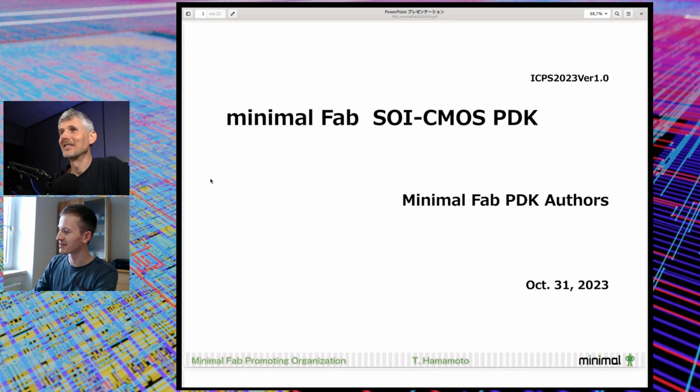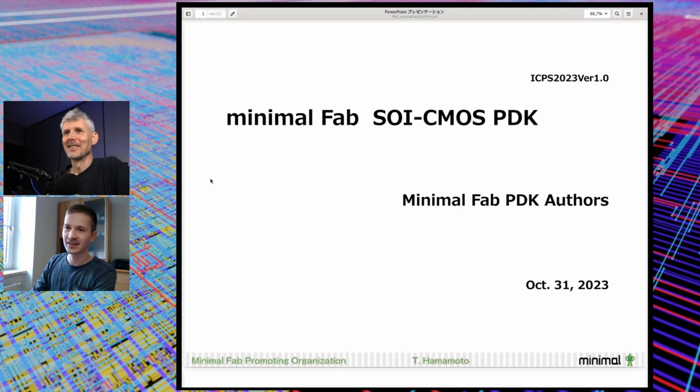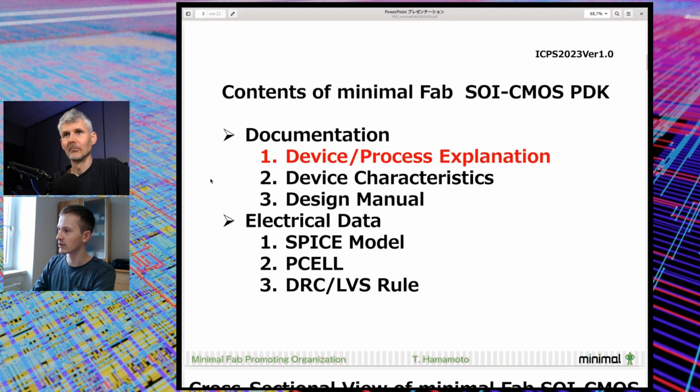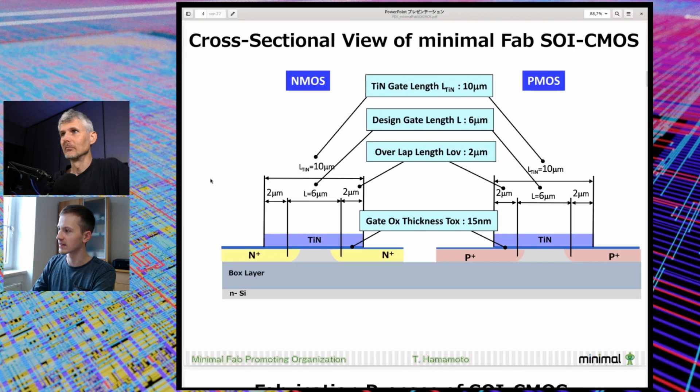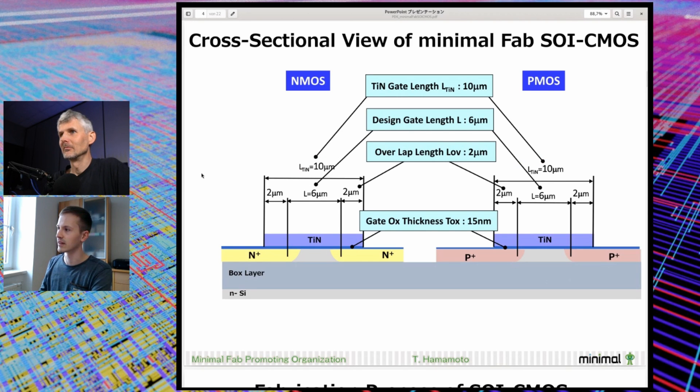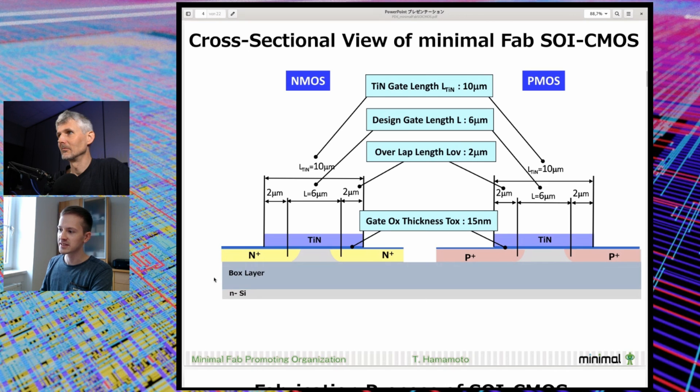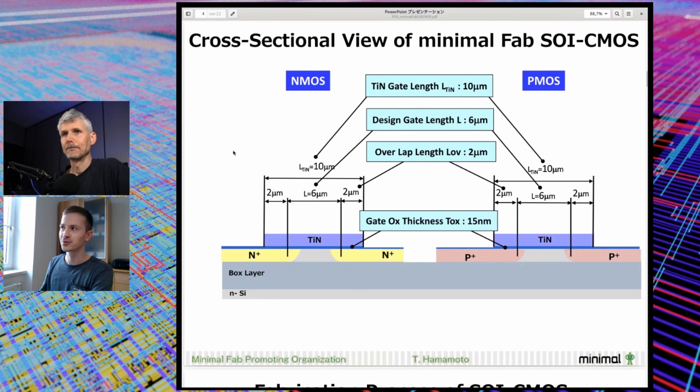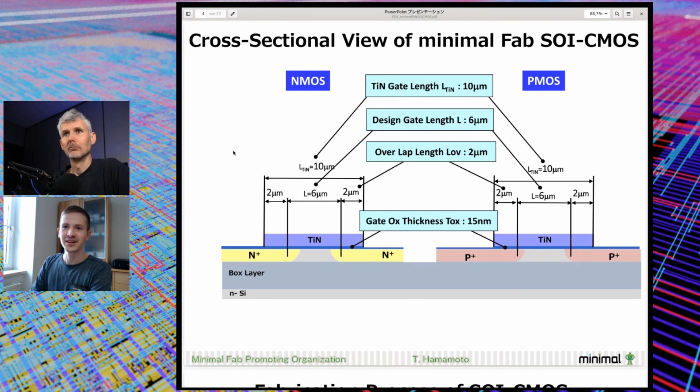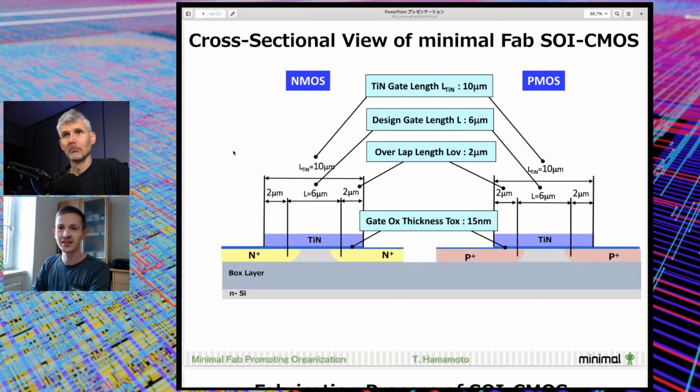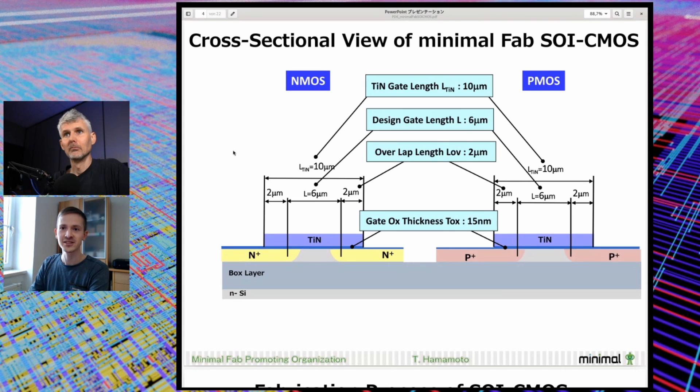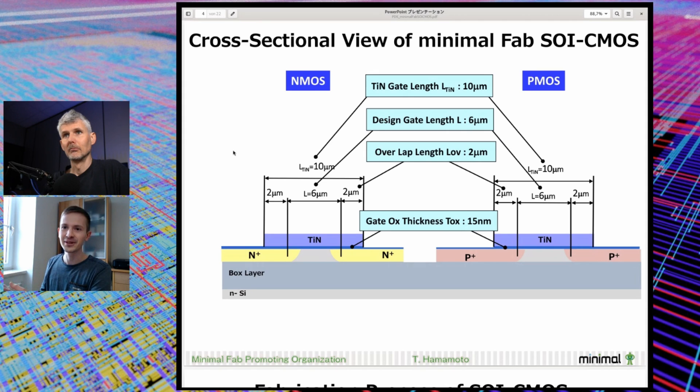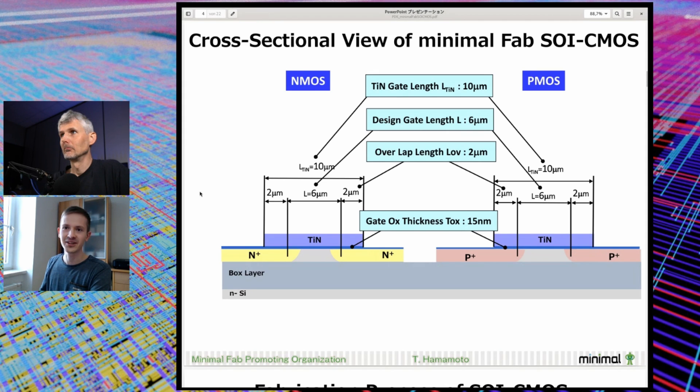It is also not just a CMOS but a silicon-on-insulator CMOS process. If you take a look at the transistors on the left side, NMOS transistor and on right side PMOS, we can see there is a BOX layer in between, so these devices are isolated from each other. You can't compare it to, for example, the first commercially available microprocessor - the Intel 4004 was designed with a 10 micrometer process in around the 1970s. This one can't really be compared because silicon-on-insulator is a completely different process.